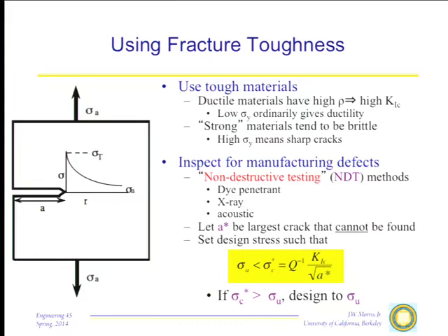Suppose you have a brittle material, and suppose you take the brittle material and you break it. Well, what has that fracture done? If it's a brittle material that doesn't yield, the fracture doesn't happen because of any deformation in the material. What you've done is you've located the worst flaw in the material. That's why, now I don't know if I put this on homework, I've used it on exams before, it's a simple little experiment. Take a glass rod, okay? Put it in a machine, pull it until it breaks.